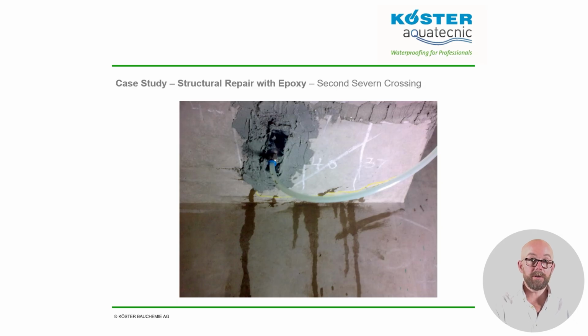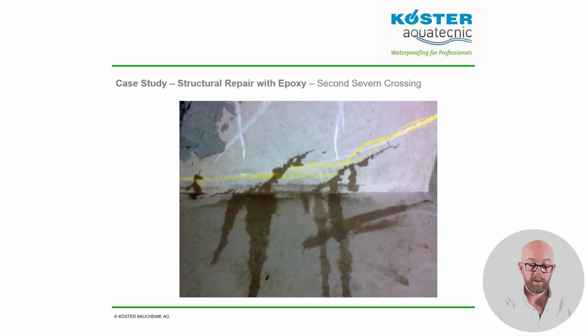Here is an area under injection. You can see some small amounts of resin running down, mainly from the intersection between the anchor block and the concrete wall. We can see that the resin has filled tiny cracks that were not even visible prior to the injection starting. The trial went extremely well, and a core sample was taken from the anchor block to confirm that the cracks were fully filled and that the adhesion to the concrete was good.